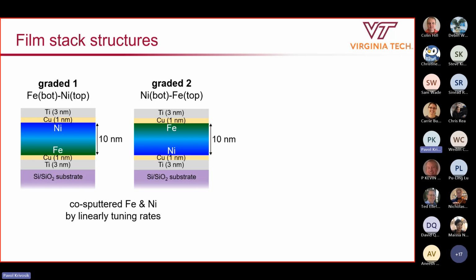Okay, so let me then walk you through the key materials, the key samples that we focused on in this particular study. So again, our aim here was to investigate the impact of this intentional compositional gradient. So we made this compositionally graded alloy film with a fixed thickness of 10 nanometers. There's really no particular rhyme or reason to why we chose this thickness. It's just a nice round number that's actually relatively thick compared to what many other folks use in the field of spin orbit torques.